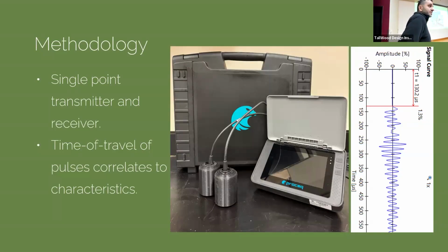We are using a set of ultrasound machines with both longitudinal wave and shear wave for CLT panel inspection. We're collecting the ultrasound signal. We send the wave and then we receive the wave through transmission, and by analyzing the characteristics of the received signal, we can assess the quality of the CLT cross-section through that propagation path.